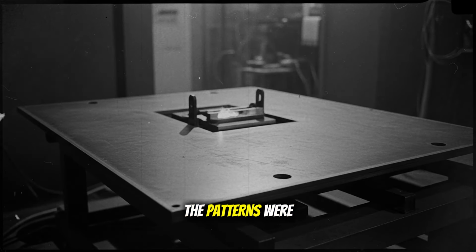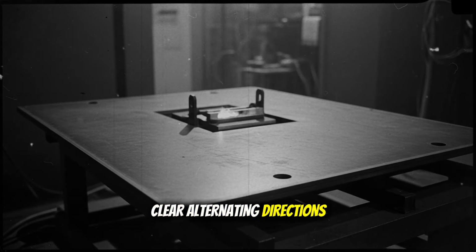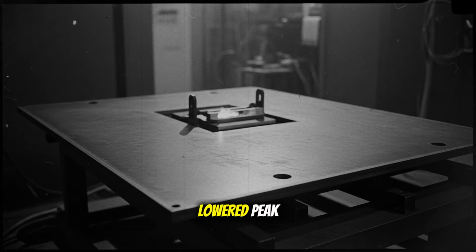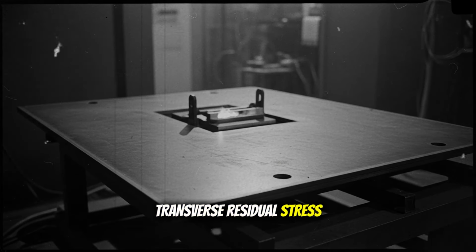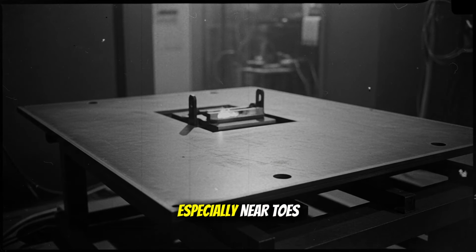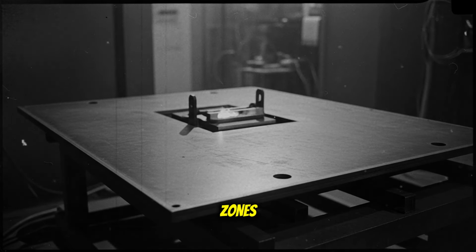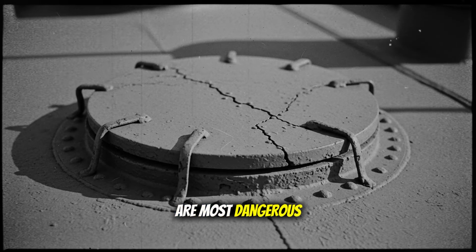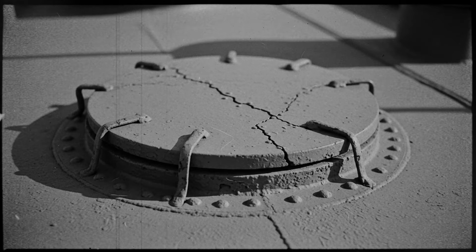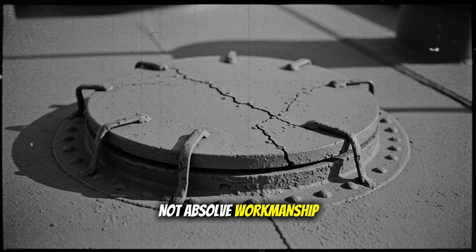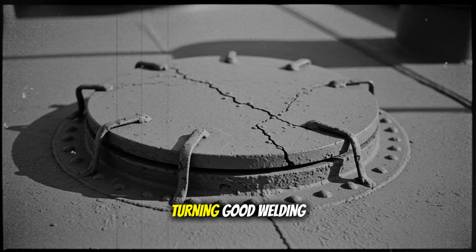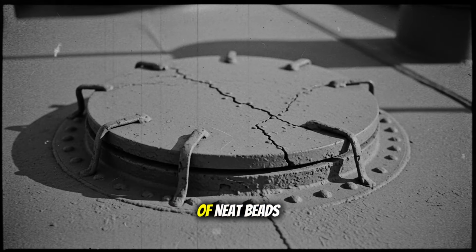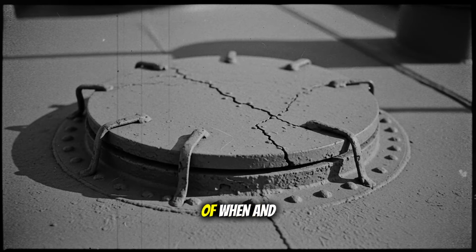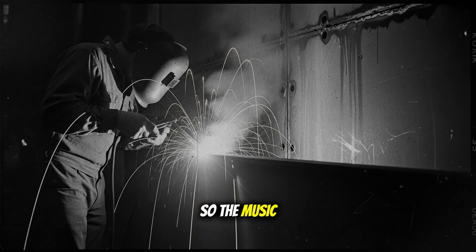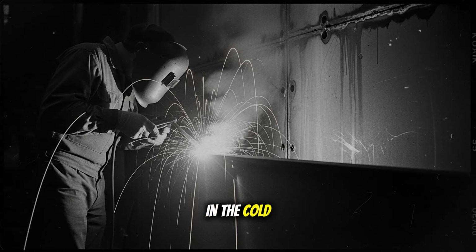Where studies compared alternate sequences, the patterns were clear. Alternating directions and distributing beads symmetrically lowered peak transverse residual stress by significant margins, especially near toes and heat-affected zones where microscopic flaws are most dangerous under bending. These insights did not absolve workmanship, they refined it, turning good welding from a matter of neat beads into an orchestral problem of when and where to play each note so the music does not sour in the cold.